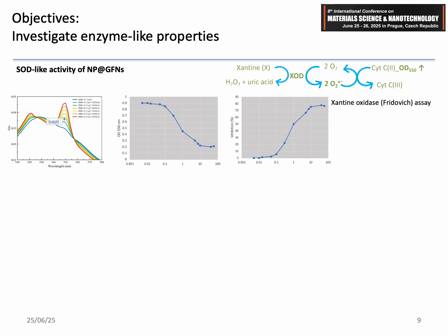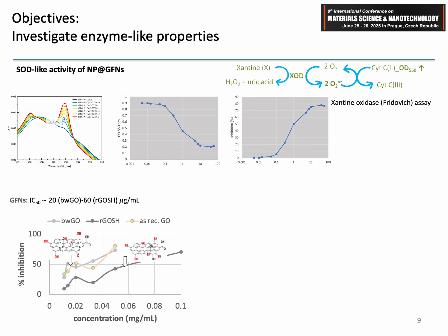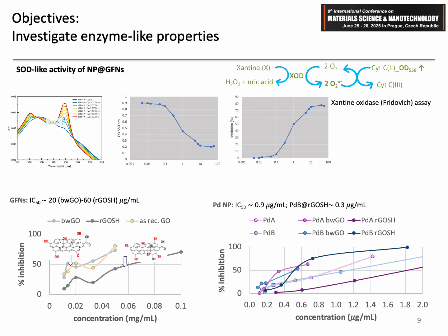time. The SOD activity is measured by how much the sample inhibits this reduction. The concentration causing the 50% inhibition is called IC50. In our results, the pristine and base wash GO have IC50 values of around 20 micrograms per milliliter. The thiolated GO has an IC50 of 60 micrograms per milliliter, and for the hybrids we see a clear enhancement. For example, the palladium B combined with the RGOSH lowers the IC50 dramatically to 0.3 micrograms per milliliter, which means 3 times more active than the palladium alone.